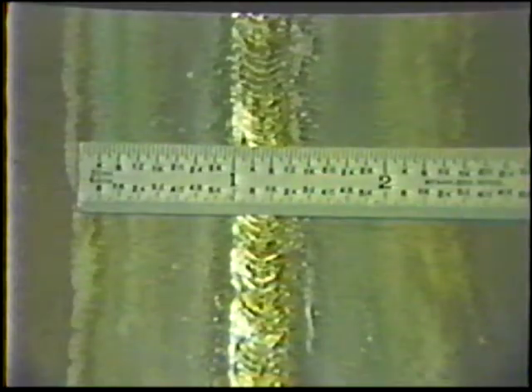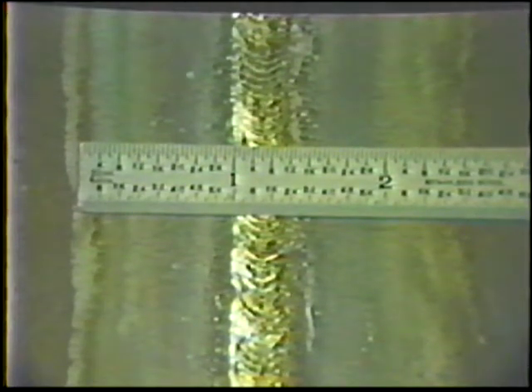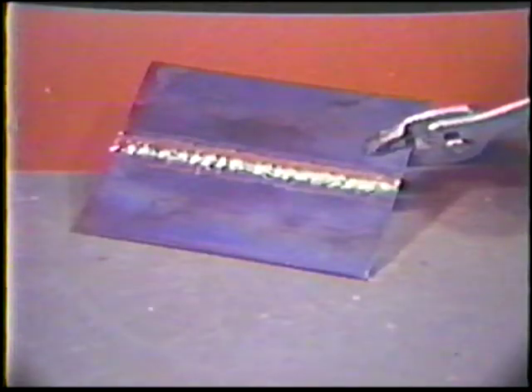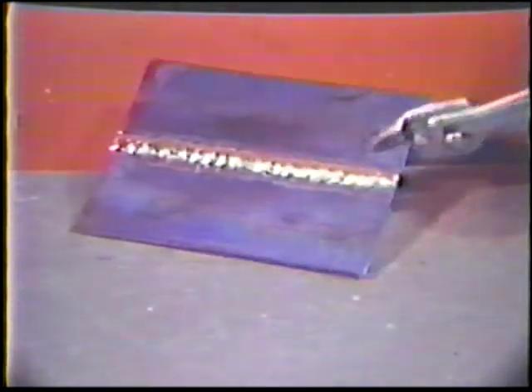The finished braze weld should flow completely into the joint, have a slightly convex face, and be about 3/8 inch wide. The joint should be completely filled on the back side. Too fast a travel speed or not enough heat will produce a highly convex bead that does not bond with the workpiece at the edges of the bead.